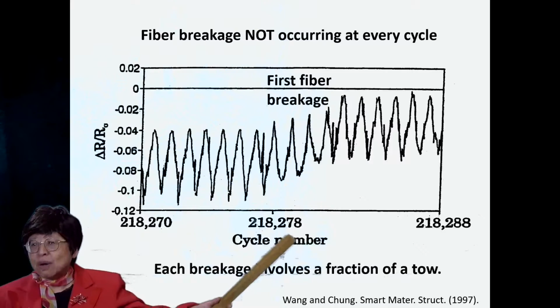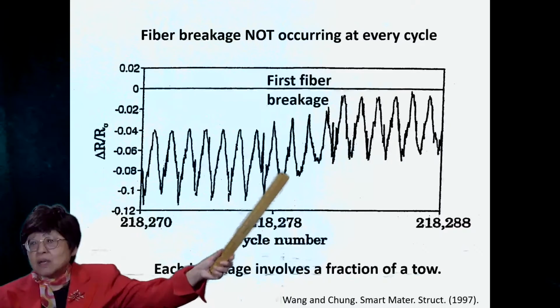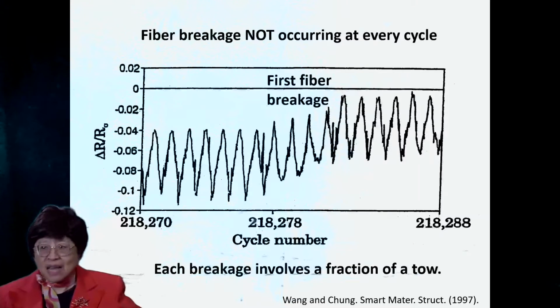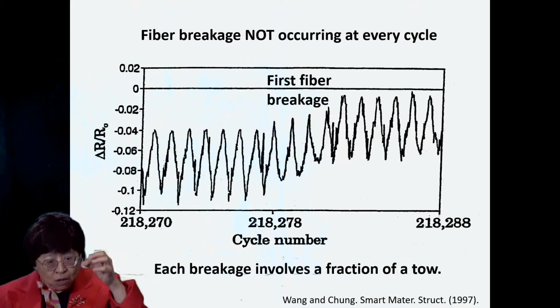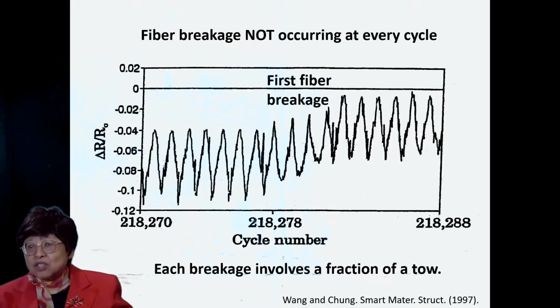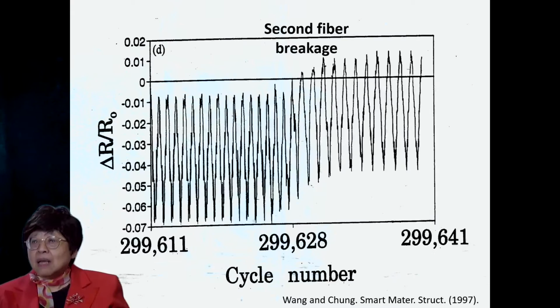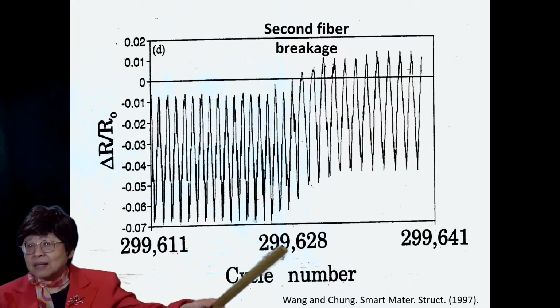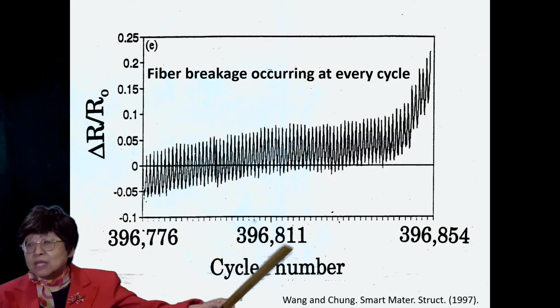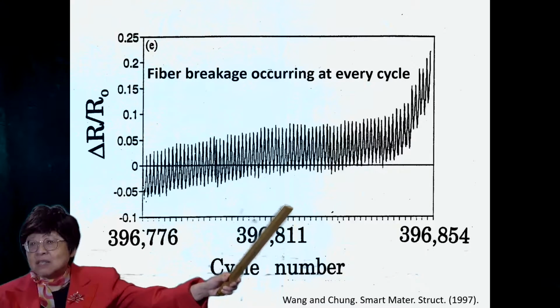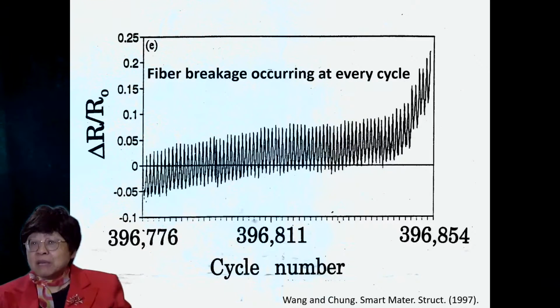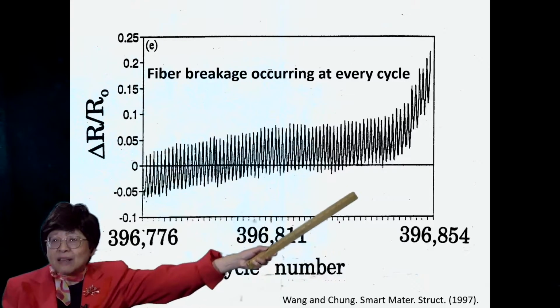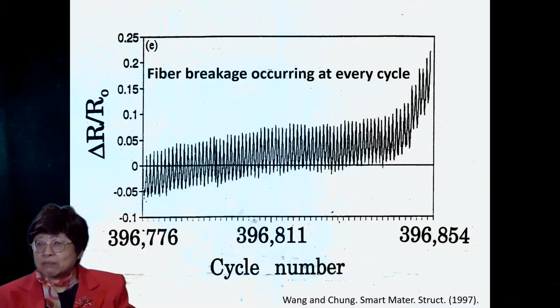And we see after 218,000 cycles, the first increase in the baseline resistance. In every cycle, the resistance goes down and up, but then the baseline shifts upward upon damage. And this is fiber breakage, and each breakage involves a fraction of a tow. This is the second fiber breakage occurring a little later. And still later, we see the baseline resistance increasing in every cycle, meaning that fiber breakage occurs in every cycle. And toward the end of the life, the resistance really increases quite abruptly.